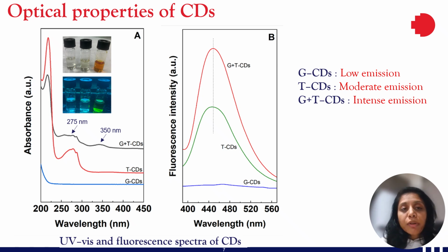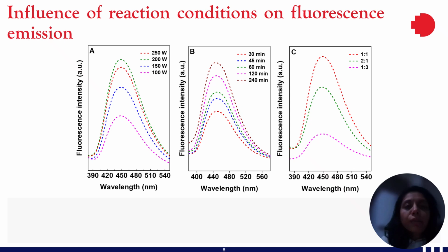However, the carbon dots that were formed from the mixture of tryptophan and glutamic acid exhibited 2 times stronger emission as compared to carbon dots synthesized using pure tryptophan, even though the concentration of tryptophan in the glutamic acid and tryptophan mixture was half the concentration that was used to synthesize the tryptophan carbon dots. This indicates that glutamic acid plays a major role in enhancing the photoluminescence of these glutamic acid and tryptophan carbon dots. The fluorescence characteristics of these carbon dots depend on the extent of carbonization, which is influenced by the reaction conditions. So the reaction conditions were optimized to enhance the fluorescence properties of these carbon dots.